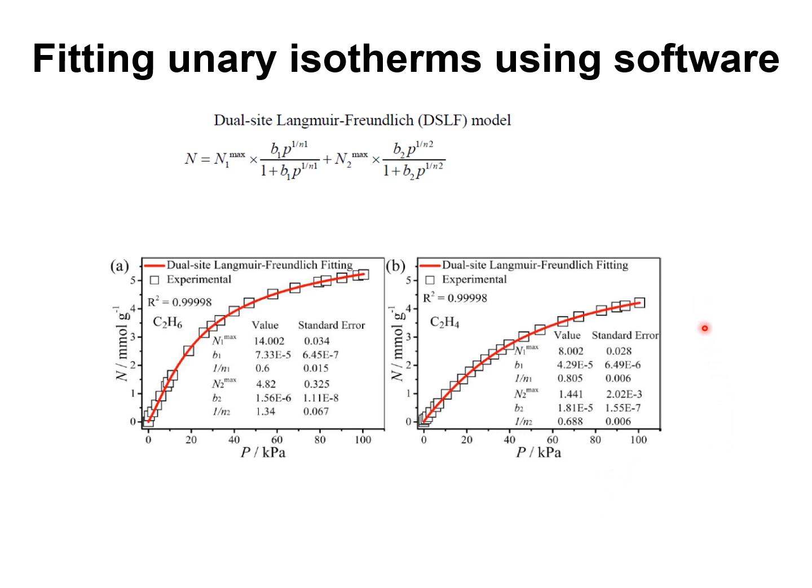So the conclusion I would like to draw is that we should only introduce the Freundlich exponents and the additional sites if it is strictly required. Use Ockham's razor and choose the simplest model and increase the degree of complexity of the model only if the data demands it.